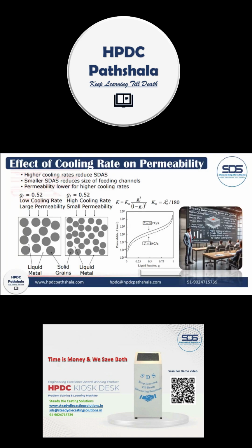A lower cooling rate creates a larger SDAS, resulting in larger feeding channels that allow molten metal to flow more easily, hence increasing permeability. The diagram on the left illustrates this concept. On the left, with a low cooling rate, we see larger solid grains and more significant liquid metal channels, indicating higher permeability. On the right, with a high cooling rate, the solid grains are more tightly packed and the feeding channels are smaller, indicating lower permeability.